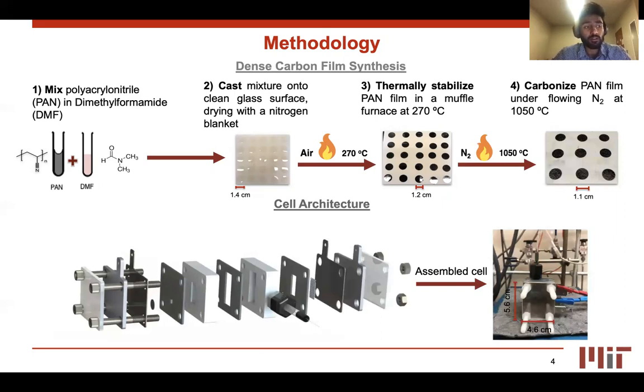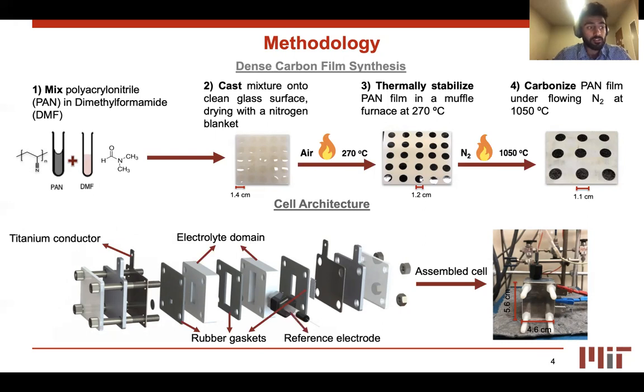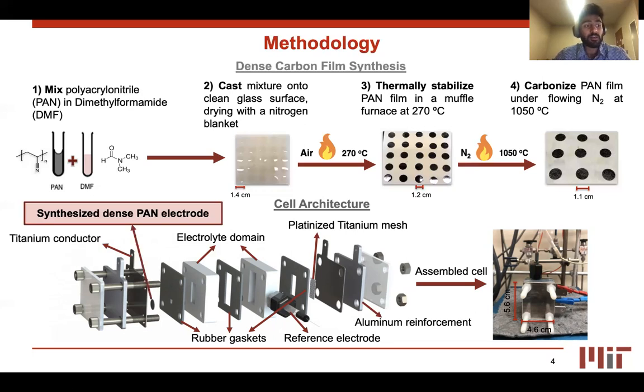The main components include titanium conductor plates on both ends, three sets of rubber gaskets, plastic compartments which function as the electrolyte domain, a port where the reference electrode is connected, a platinized titanium mesh that functions as the counter electrode, and aluminum plates on both ends as a mechanical reinforcement for the overall cell architecture. And finally, the synthesized dense carbon electrode disc that functions as the working electrode to complete the three electrode voltammetric analysis.